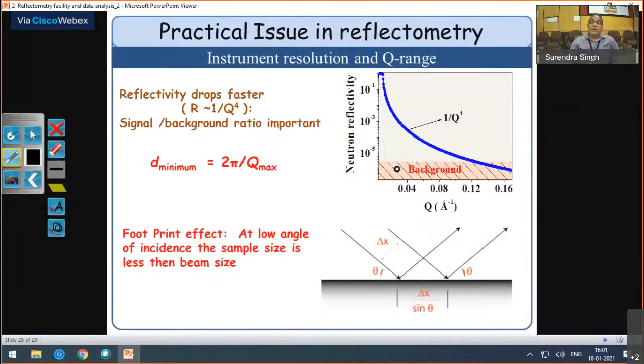We can have stray neutrons coming from here and there near the instrument, which increases the background. Also, the kind of sample you are using contributes to the scattering. You might have heard of incoherent scattering, which completely gives you the background. So depending on the sample, we have this issue of how much Q you can measure in the reflectivity.